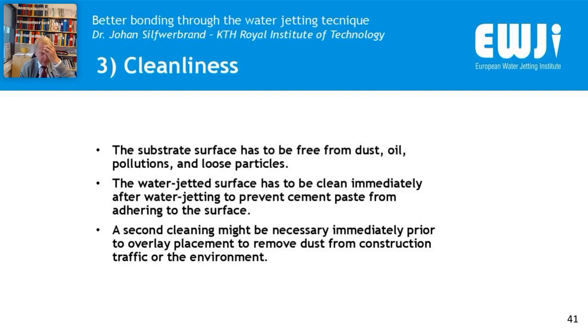The water jetted surface has to be clean immediately after water jetting to prevent cement paste from adhering to the surface. When you are using water jet technology, then you are removing a lot of concrete. And it is not always the case that all the cement has hydrated in the old concrete. So there is a risk that you are exposing unhydrated cement surfaces to water. And then if you have loose particles, they may adhere to these free cement surfaces, and that's why it is so important that we remove the debris after water jetting, and do it quickly.